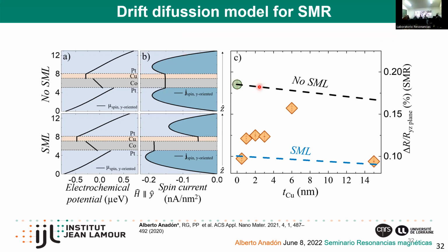If we have no spin memory loss, we would follow something like this. So basically, copper will be almost transparent, and we will see no changes in the spin Hall magnetoresistance. If we add the spin memory loss, we will be somewhere here, but we cannot explain what's going on in the middle of this thickness evolution only using spin memory loss. So we believe that there is a spin current generation in the interfaces due to these processes that I described at the beginning, due to spin filtering and spin precession.